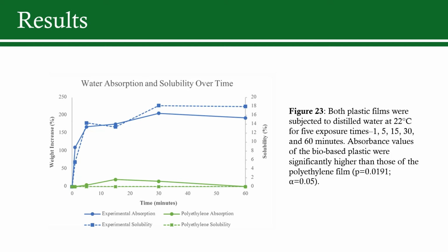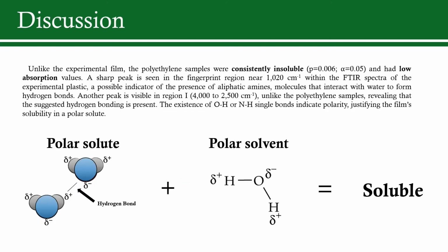60 minute marks. The polyethylene film had a 0% solubility for all trials, but the solubility of the film reached its maximum at the 60-minute mark with 18.2% solubility. It may be inferred that this trend would continue to increase directly with time. Further investigation suggested the presence of aliphatic amines, which are molecules that form hydrogen bonds in this scenario. A secondary peak in the first region of the spectra indicates that the suggested hydrogen bonding is present.